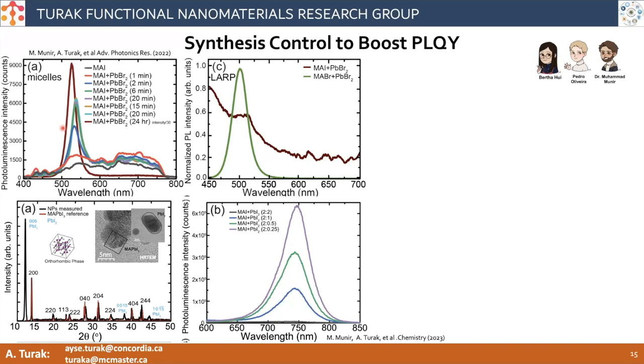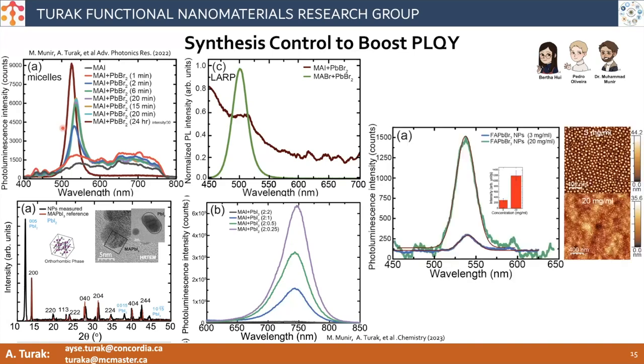that we're able to get out of these sorts of materials. And not only that, we're looking here at the emission from just a monolayer array of nanoparticles on the surface. They're separated, they're about 6 or 7 nanometers in diameter, and they're separated by about 30 to 40 nanometers of spacing. And we can still see the emission from these sorts of films.